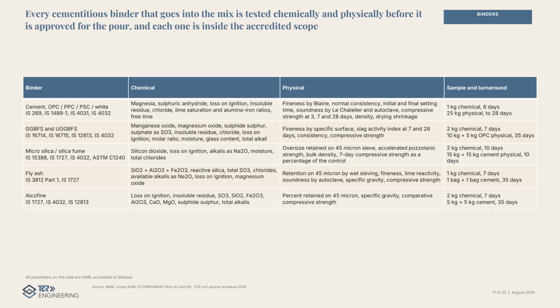Every cementitious binder that goes into the mix is tested chemically and physically before it is approved for the pour. And every parameter on this list sits inside the accredited scope. Cement runs a full chemical panel under IS 4032 and a full physical panel under IS 4031 out of the 28-day strength. Slag, microsilica, fly ash and alkafine each carry their own chemistry and their own activity or reactivity index. The point is not the individual test. It is that a mix design is only as good as the weakest binder in it. And you cannot know which one that is without measuring all of them.